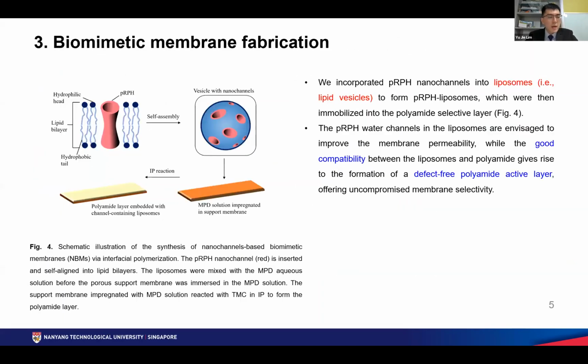Now, let us take a look at the biomimetic membrane fabrication methodology. First, we incorporate the PRPH nanochannels into the lipid bilayer, and through self-assembly, the channel containing liposomes are formed. These liposomes are then blended with the MPD diamine solution, and thereafter we perform interfacial polymerization, IP, to encapsulate the channel containing liposomes into the membrane selective layer, thereby forming the nanochannel-based biomimetic membrane, NBM for short.